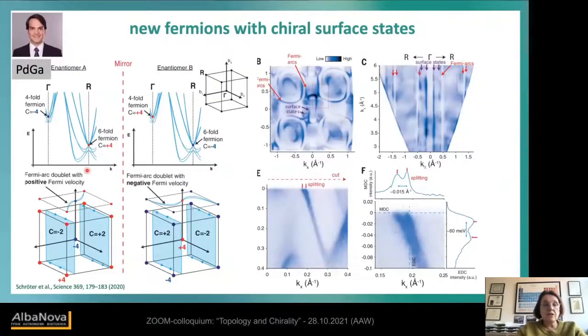So what was also interesting here, because these compounds have higher Chern numbers, this is more for the experts in chirality. And this was exactly what we could show here, because we had this platinum, no, this was also palladium, gallium, so we could show the splitting in these crystals, which was a proof then that this is a Chern number in the case of the surface.